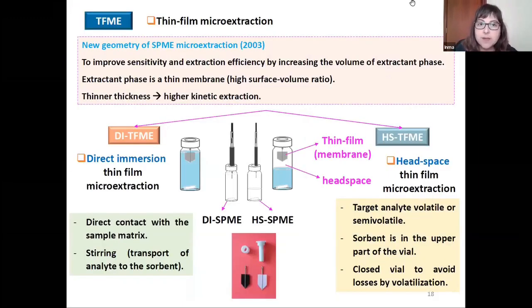Then we have the thin film microextraction, which is a new geometry or format of solid phase microextraction developed in 2003 by the Pawliszyn group in Canada in order to improve the sensitivity and extraction efficiency by increasing the volume of the extractant phase and reducing the thickness of this phase. In this case, usually a membrane is used. As we can see in the slide, there are two modes of thin film microextraction, as in solid phase microextraction, which are thin film immersion and headspace thin film microextraction.